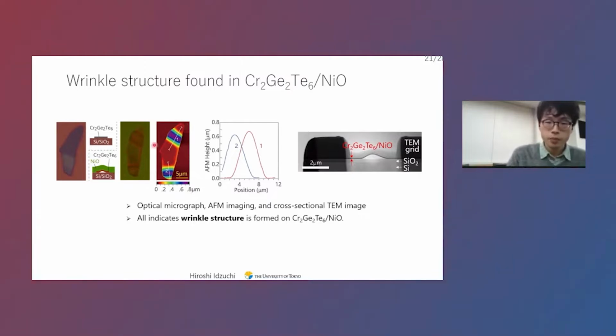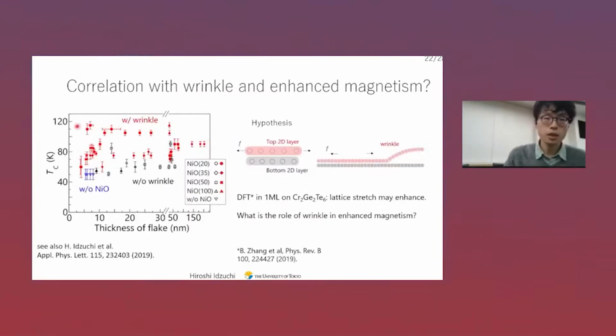And then we examine by AFM and see some topography. Actually, the height is high in this additional place. And then we also do cross-sectional TEM imaging, and indeed, this has some structure corresponding to this area. And if we measure Curie temperature with a lot of the CGT/NiO flakes,